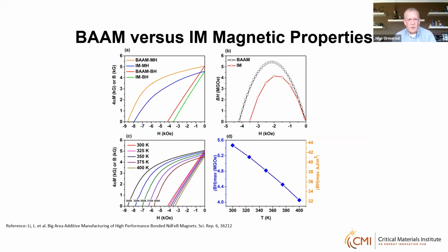Here are some of the magnetics that were achieved, and I'll just point out this top left-hand demagnetization curve. What's interesting, and was surprising to us, is the orange demagnetization curve is from the BAAM extrusion process. The blue is from a conventional injection molding using the same compound. So obviously we were surprised to see that the BAAM process actually had better properties in terms of remanence and coercivity and energy product than the injection molding process using the same compound. We think what's happening is there's a much shorter residence time of the compound in the BAAM process compared to injection molding. This is limiting the particle mechanical damage and oxidation and results in improved properties.